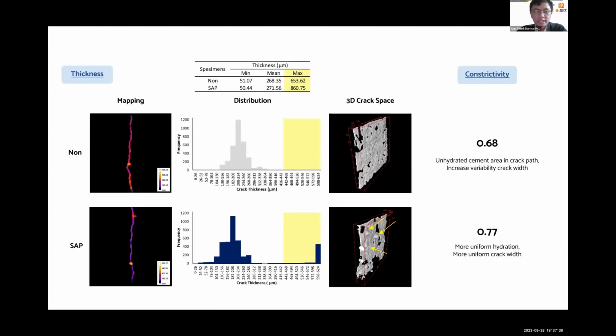Through X-ray CT, we can also observe crack geometry properties like distribution and connectivity. The distribution is similar, but the maximum thickness for the SAP specimen is attributed to pre-soaked SAP, which is bigger when it absorbs water. And from the 3 dimensional crack space, connectivity can be quantified. The SAP specimen has a connectivity value closer to 1 than the non-SAP specimen, because uniform hydration makes more uniform crack width.